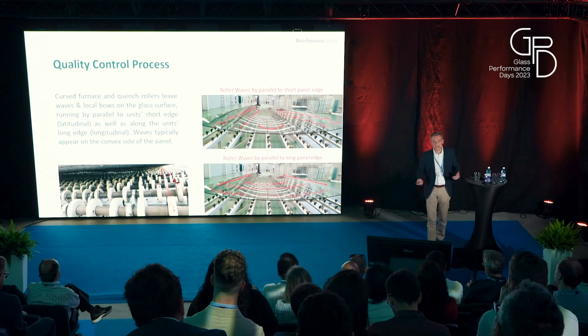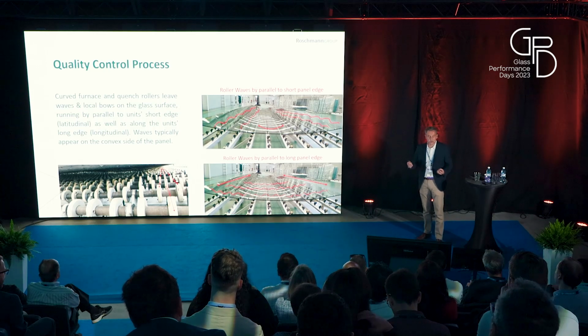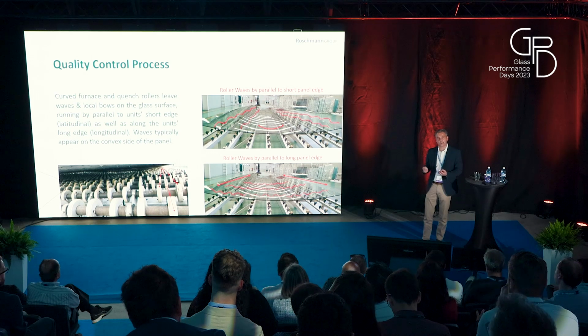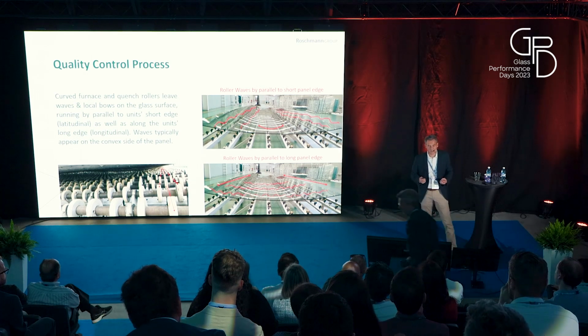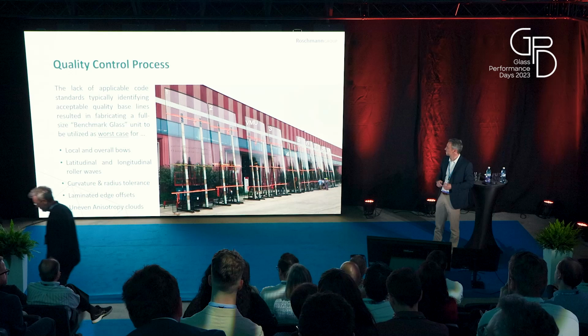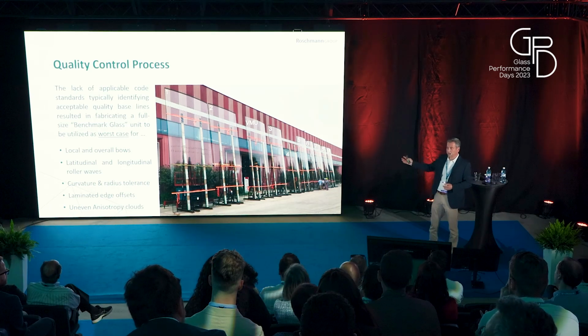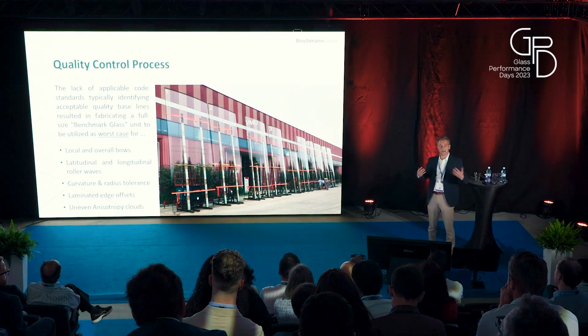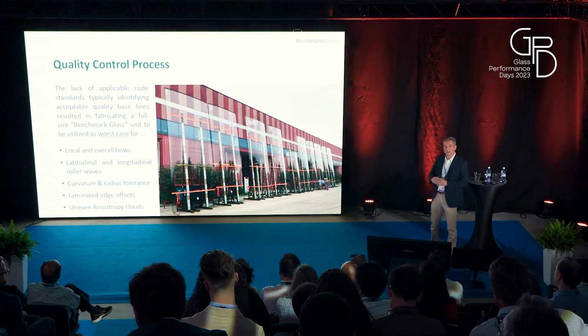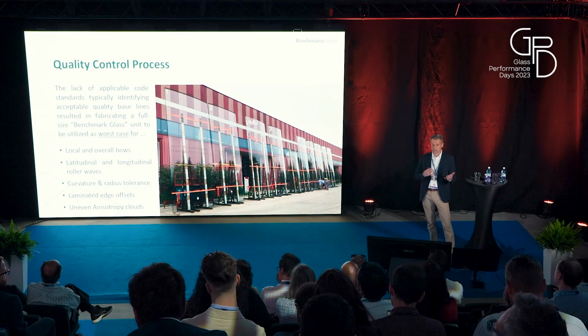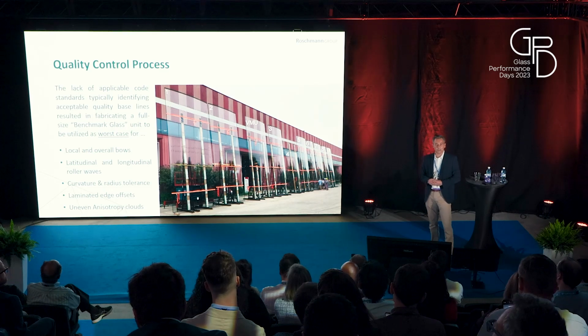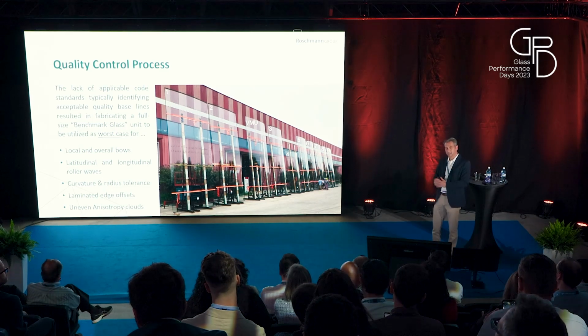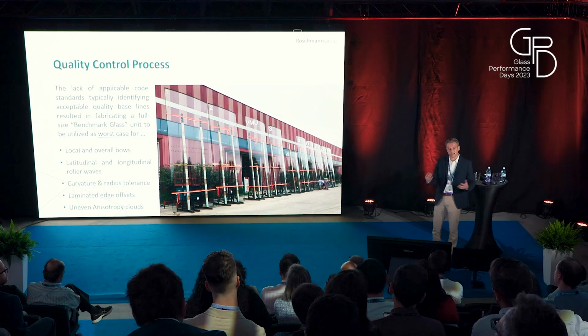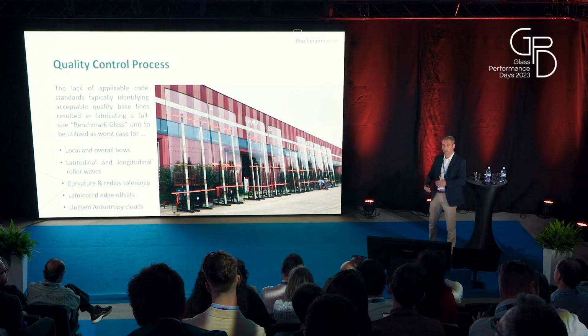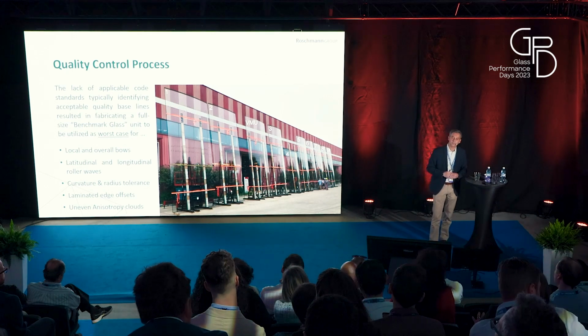And that's also why it is so important to create benchmark units in order to track this kind of quality measurement process. Especially if we are talking about large glass, bent glass, temper bent glass, we are missing standards and codes. So every time we are missing standards and codes, what are we doing in order to benchmark the quality? Because we want to create a kind of quality benchmark. We are creating benchmark units, full size, in order to set the baseline for the quality.